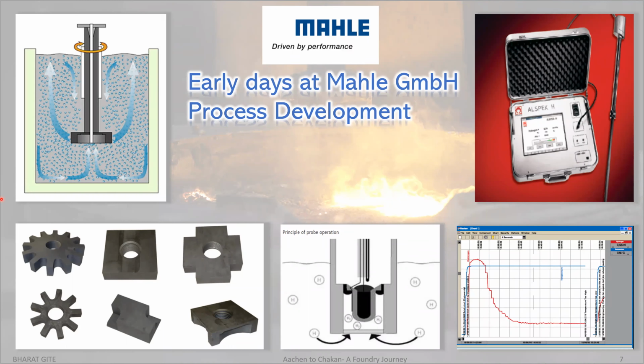It is built around an innovative electrochemical sensor that is capable of rapid and real-time measurement of hydrogen. Having a base of ceramic material, calcium zircon oxide, it has two different electrodes. One is called the reference electrode and the other is called the measuring electrode. We can see the schematic diagram here, in this area where the probe is deep in the aluminum melt. Hydrogen solubility strongly depends on the temperature. Therefore, the melt temperature must also be measured in order to calculate the dissolved hydrogen level. And here you can see there are two curves, one is the hydrogen content and the other one is the temperature, and it was finding the correlation between the temperature and hydrogen content in the melt.